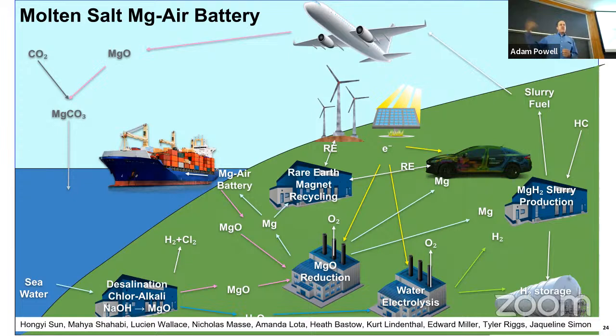began with Hong Yi working with Christian Faria on the direct carbon fuel cell. And we thought, okay, what if we put some liquid magnesium on top of this, so that as the CO2 came out, the magnesium would grab the oxygen and oxidize, and the carbon could go back into the liquid metal. So we'd have kind of a closed loop, carbon, CO2, back to carbon to CO2. The magnesium would turn into magnesium oxide, and we could use its extraordinary energy density to maybe propel ships across the ocean. Well, that was a terrible idea because a lot of energy is lost in that CO2 plus magnesium to magnesium oxide plus carbon reaction. You only get about a third of the energy out of it at most.